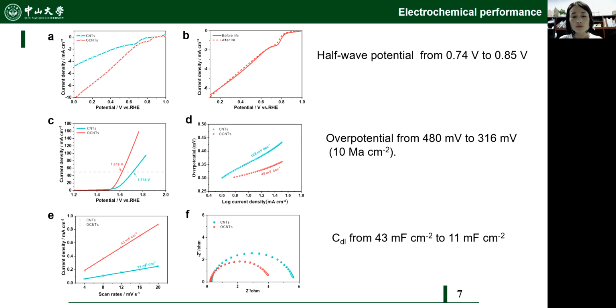A greater amount of active sites are created after introducing oxygen functional groups. In addition, the reaction kinetics of OCNTs is significantly enhanced. These results reveal that the electrocatalytic performance of carbon material can be optimized by the oxygen functional modification.